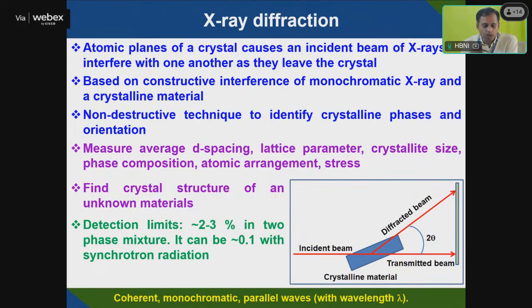And then if you come to atomic planes of a crystal, if you take this as a substrate, on this substrate there are lattice planes. If you have lattice planes, they are periodic in order, and the atoms are periodically arranged on each lattice plane. So what happens when the atoms are periodic? Then your X-ray is falling here. For example, X-ray is coming, then it will be diffracted into the other direction. You will see the incident beam and your diffracted beam making an angle 2 theta with the transmitted beam. So this is the angle of diffraction, 2 theta.